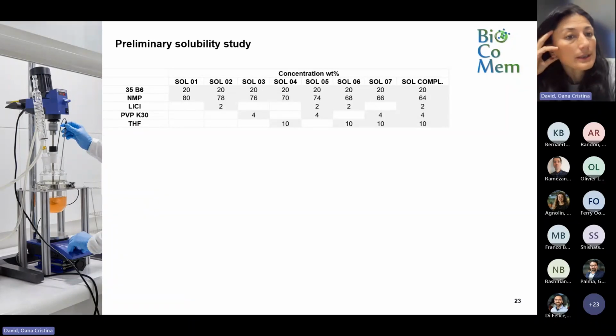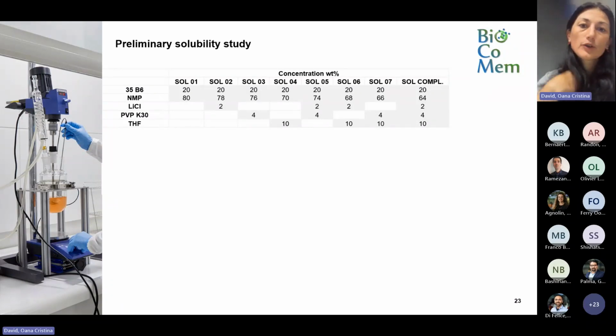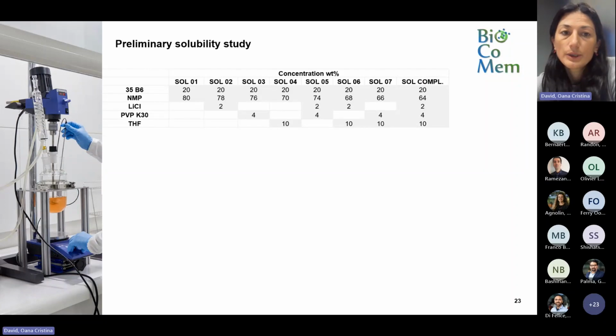So here is 35B6, this polymer here, the one that was synthesized by the University of Maastricht at lab scale. It's the one that, based on flat sheet NIPS process and gas permeation results, we decided might be the best to scale up. But before we actually asked Arkema to scale it up, we wanted to check if we can actually make a hollow fiber. We had some polymer and we could make a small spinning experiment with not so much quantity of polymer. And before doing that, we needed to know what would be a good polymeric solution formulation